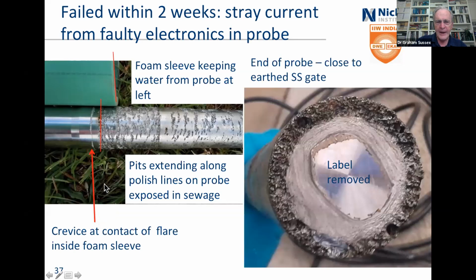Okay. How do we know it was actually galvanic? Well, because it was stray current, not galvanic, because it was very quick. This is the end of this pipe. This was a plate that was on the end. Around here is actually the end grain attack of the end of that tube, because it's fairly close to the earth stainless steel gate. Here, there was a label, so there was no corrosion under that, but this is the end plate sealing the end of that pipe. And as you can see, it's corroded away there.